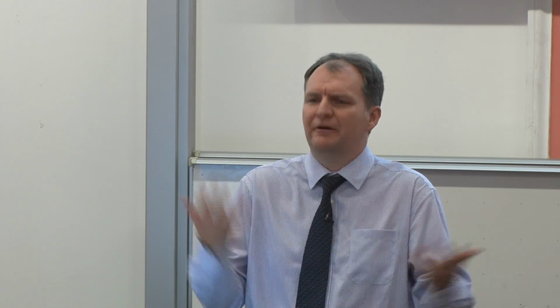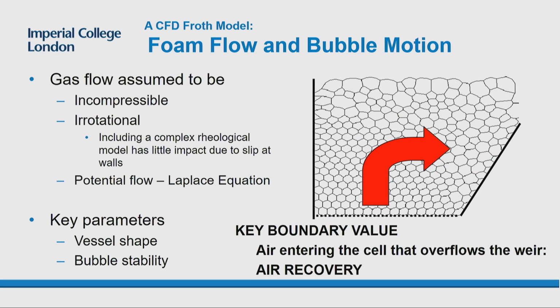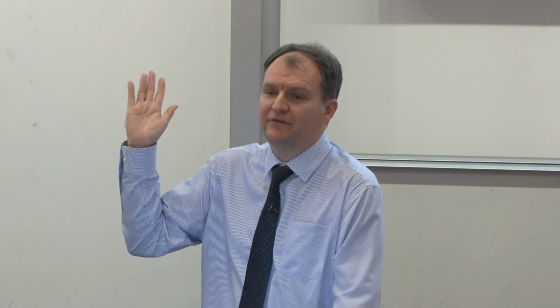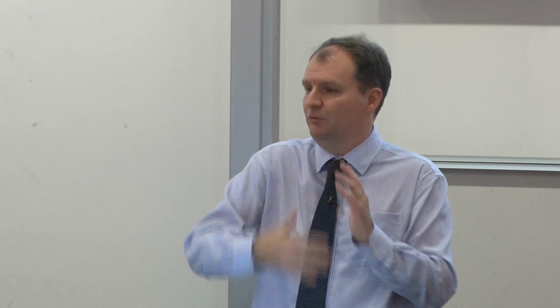So, in terms of the gas motion, we assume that it's incompressible, which might seem a very strange assumption for air, but the liquid content of flotation froths is comparatively low, and they flow comparatively slowly, which means that compressible effects actually aren't that important, and including them would make the models much, much nastier. We also tend to assume that they're irrotational, which again is a slightly strange one for anybody who knows about rheology. Irrotational typically implies inviscid flow, that you don't have any viscous effects. But we still get quite a good approximation, even though there are very strange rheologies in these systems, and that's because there's a lot of slip at the walls. These froths slip along the walls. They aren't pinned at the walls, and so the internal rheological effects don't make a giant difference to the behavior.